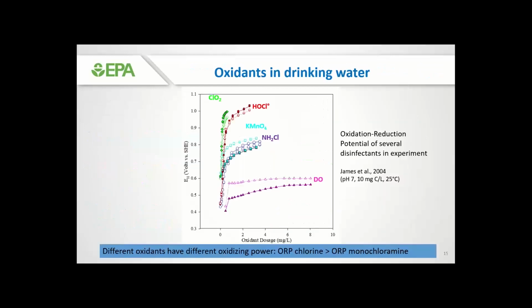I talked about ORP earlier. ORP is really important, but we don't typically measure it in drinking water. It is the oxidation reduction potential of the water, and it's highly dependent on the disinfectant type and dose. These are measurements from an older experiment at the EPA, where you can see on the x-axis the oxidant dose in milligrams per liter added to the water versus the ORP measured on the y-axis.